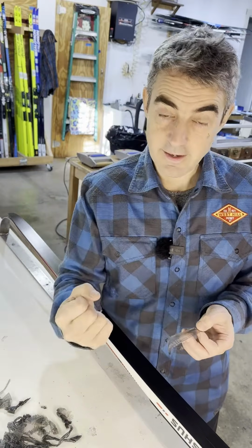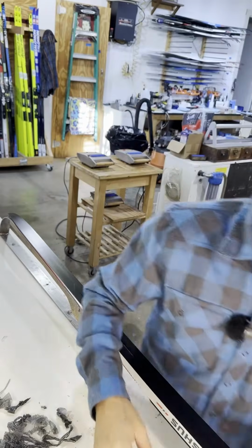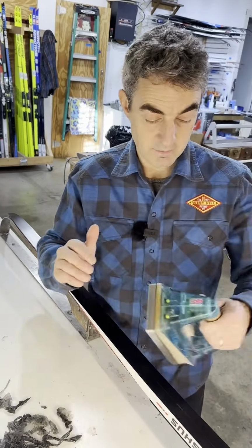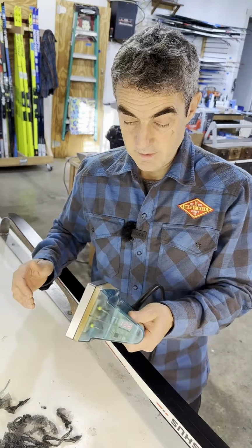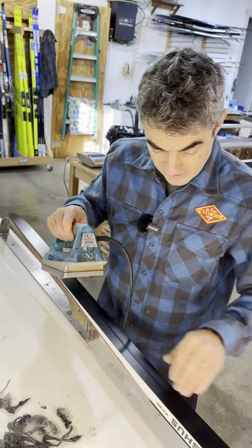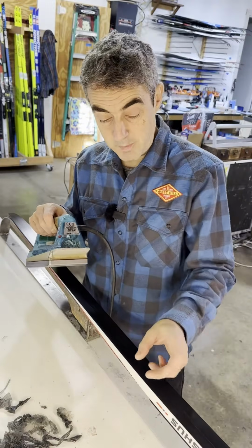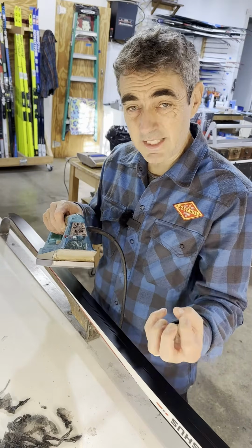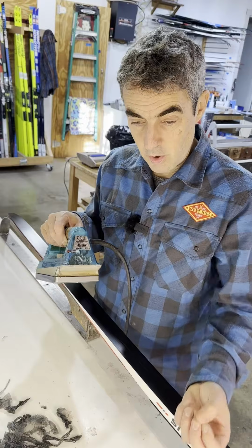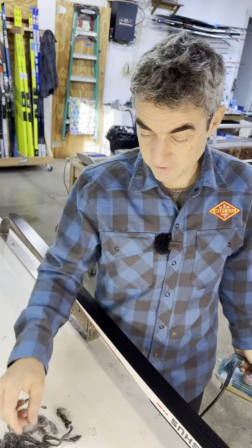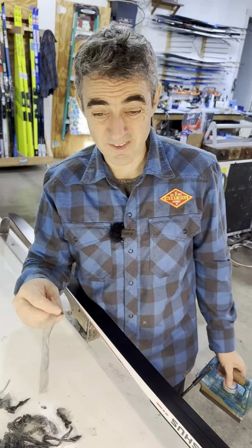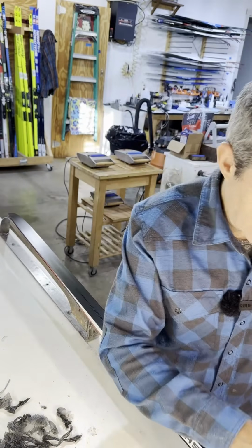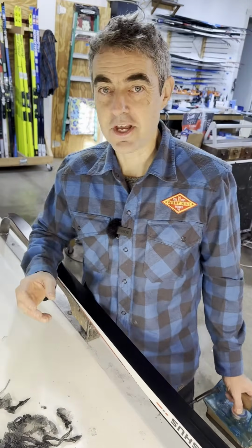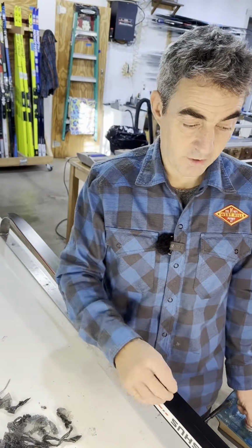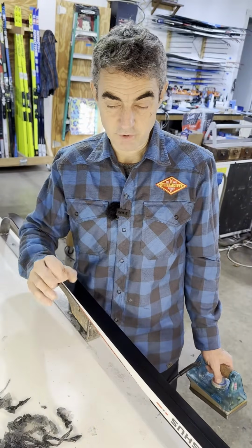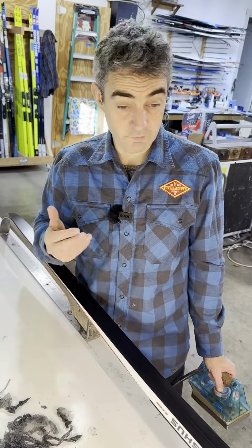As you have the iron in your hand and it's got heat on it, right now it's at 132 degrees, all right? So we have the iron at a temperature where, with our little experiment, we saw the base start to really, really rapidly crinkle up, and that's, we know, getting up into the secondary glass transition phase of the amorphous material, and that's quote-unquote burning the base. It is a process like searing your steak. You want to do it sometimes, and our base hardening process is exactly that, because it results in a harder, more uniform finish, and it's faster on the snow.